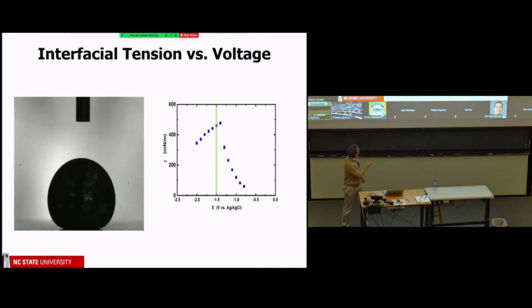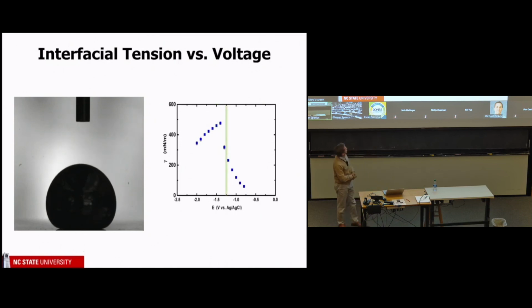So here's our experiment. Here's the droplet. There's a little electrode just poking through right there. When we don't do anything, here's that surface tension, about 500. Remember, water is 70. This is when we're doing nothing. Again, it looks like we're applying a voltage, but we're doing nothing. This is what's called the open circuit potential. So here we go. We start the experiment and apply a little bit of positive voltage, a fraction of a volt, and the droplet starts to squish, and it's completely reversible. We're getting huge changes in tension, and it's completely reversible.